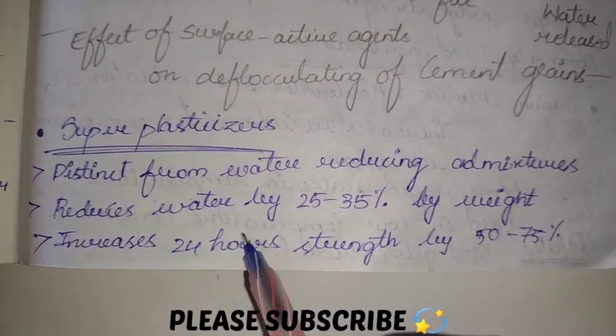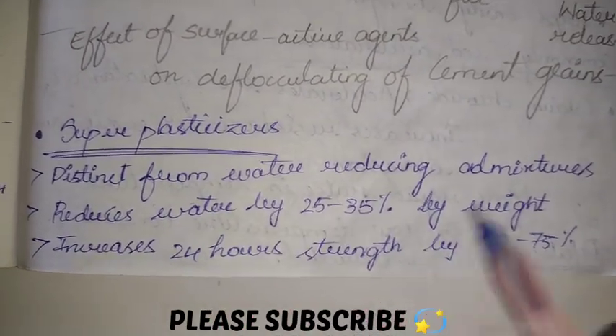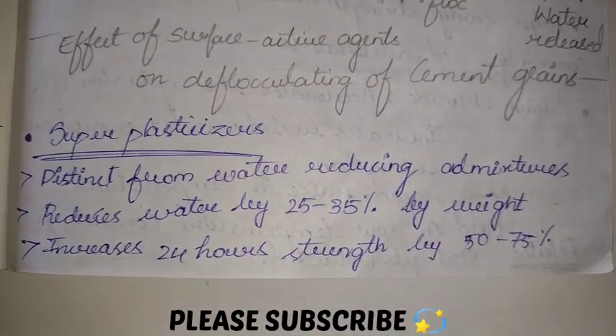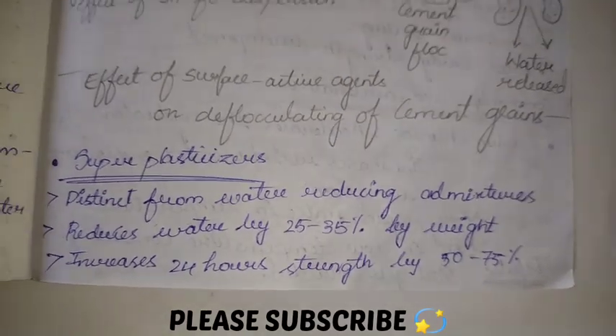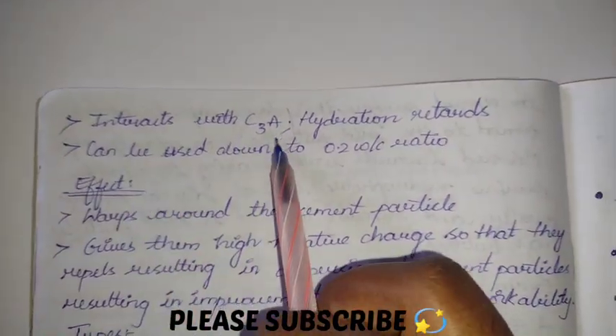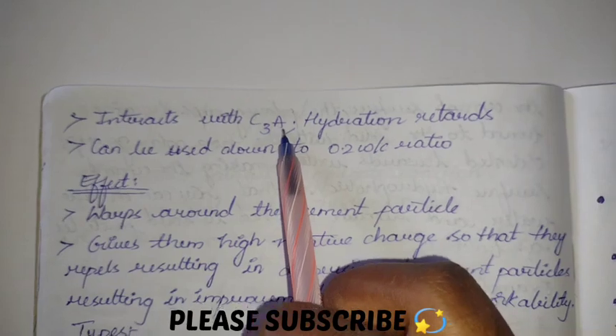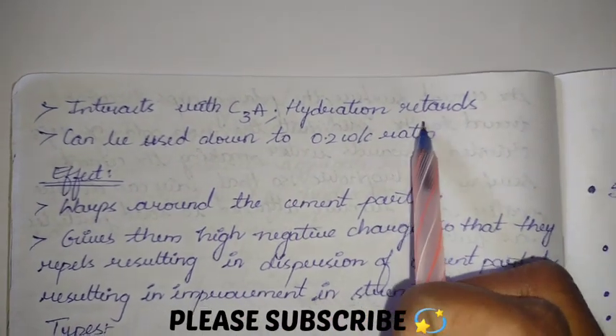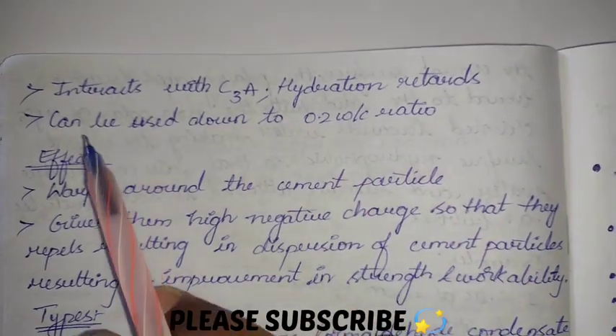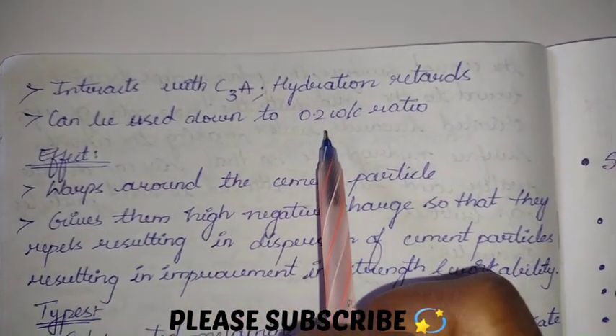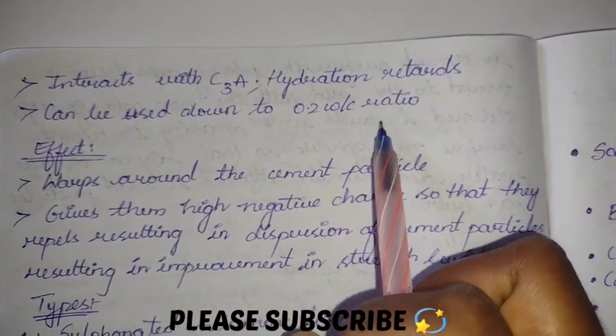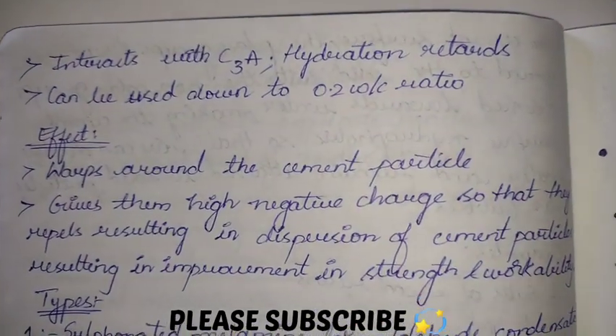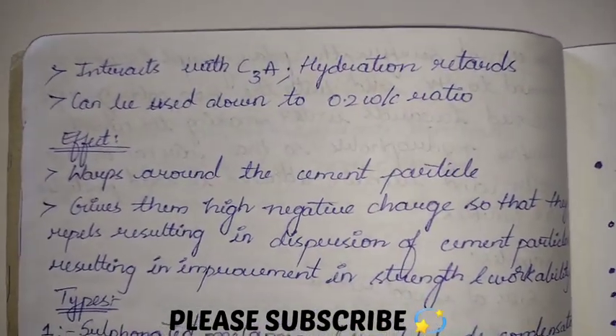Okay, it reduces the water content by 25 to 35%, whereas plasticizers reduce by 5 to 15%, and it interacts with C3A, that is tricalcium aluminate. Hydration retards. Here there is retardation of the hydration. Okay, so it can be used down to 0.2 water cement ratio. So whenever very low water cement ratios are there, even in that case it can be used.